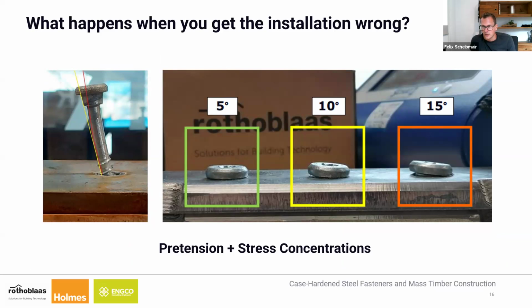But what often happens is if the install guidelines aren't followed, the contractor will actually go ahead and just keep applying torque until that screw head sits flat against the steel, because then everything looks perfect and the engineer comes along and there's no problems. But what that means is that there's definitely an over torque in the screw, and it's likely that you've reduced the capacity of that screw below what the designer, I guess, intended in their design.